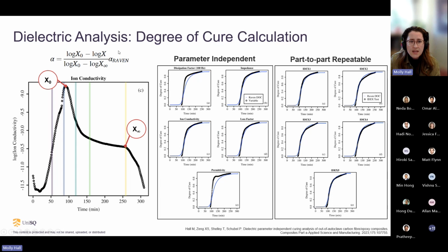I will also say that this equation, if you ignore this alpha Raven, assumes you reach 100% conversion, which we know is not the case. So we do normalize this by either a simulated or a measured degree of cure. So if you measure degree of cure using DSC, for example, that can normalize this as well. But I used the Raven simulation to do this. So this technique, as I said, is also parameter independent. We also showed that it is quite repeatable from part to part across different replicates.